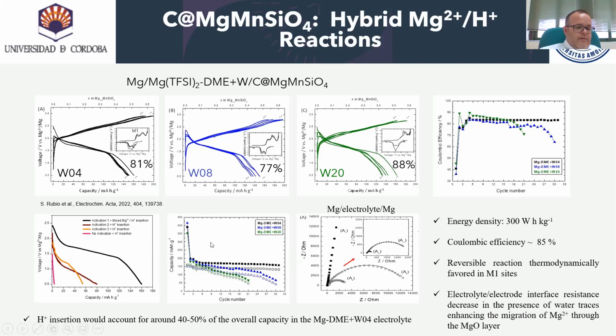The capacity retention is better for the electrolyte-based cell using few water traces, as represented here. In the initial cycle, proton insertion would account for around 40 to 50% of the overall capacity. The occurrence of a hybrid magnesium-proton electrolyte solution could provide superior mobility as compared to the sluggish magnesium ion. Indeed, other authors have already proved that the magnesium ion migration energy barrier of V2O5 can be decreased gradually with increasing proton concentration.